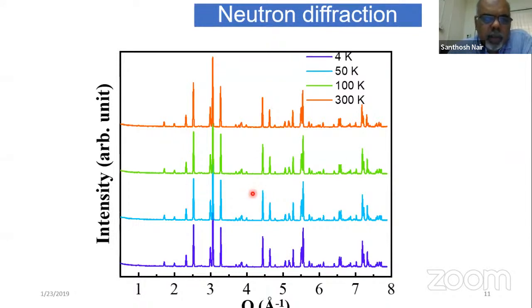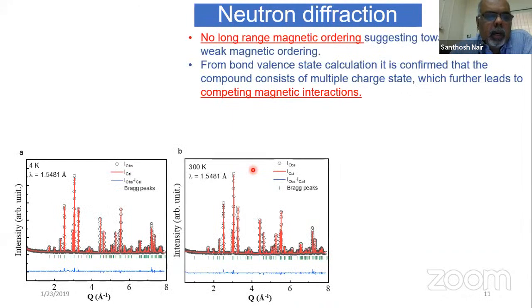If you have an antiferromagnet, you will sometimes see an additional peak. If you have a strong ferromagnetic system, you will see an increase in the intensity at lower temperatures. But our analysis of these data shows that there is no presence of long-range magnetic order, neither ferromagnetism nor antiferromagnetism. So that's the essence of the idea we get from the neutron diffraction data, right?